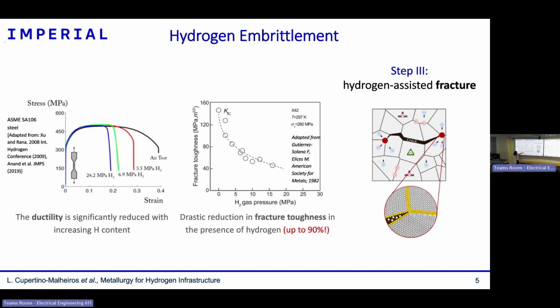And what's plotted in this middle graph is fracture toughness, which is proportional to the energy necessary to fracture a material. Here is plotted this fracture toughness as a function of hydrogen pressure. Again, the same material, this is a low strength pipeline steel that can be in our natural gas grid, being tested. And here, the highest value of fracture toughness indicates that the material is difficult to break. You need to provide lots of energy. And at lower values, it breaks easily, which we call brittle. And here you can see how much hydrogen gas pressure reduces this fracture toughness.